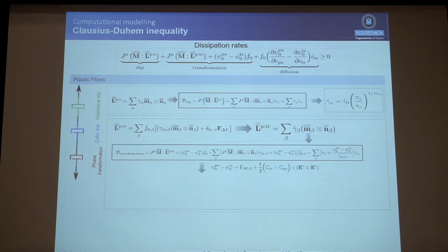Taking this into account, we have this equation that relates the free energy of the parent phase minus the free energy of the transformed phase, which is the stacking fault, and the change of elastic energy, because it has different elastic constants. If we include that into the driving force here, we get to this kind of power law, which is the same as the plastic one, but it has a kind of back stress, which is related with the stacking fault energy, which depends on the chemistry.